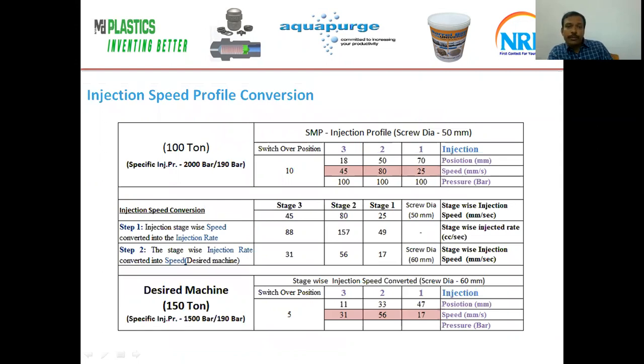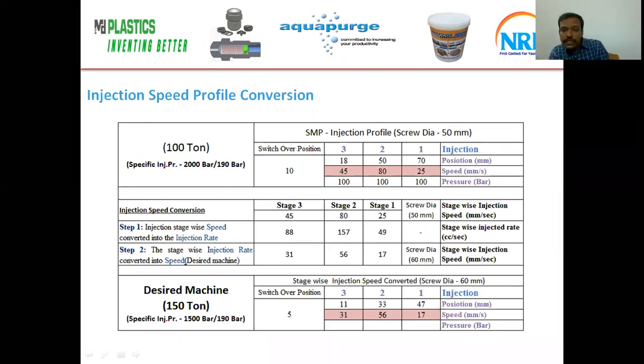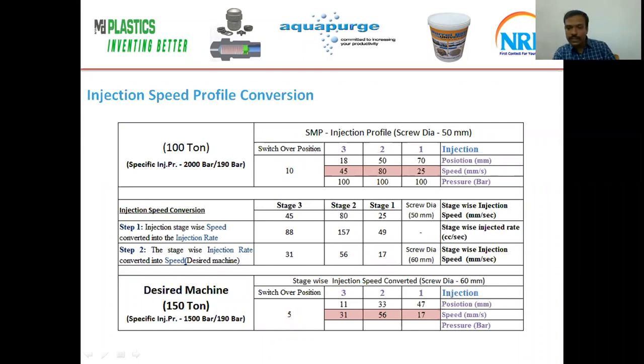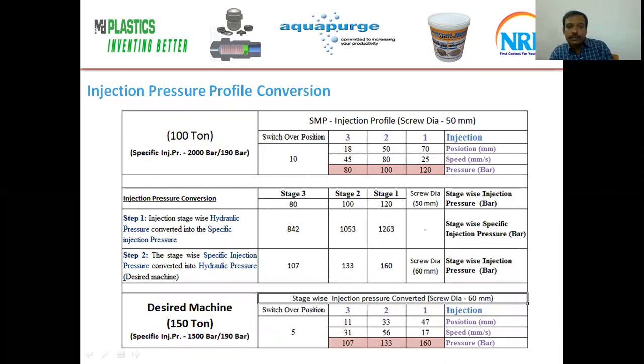Next, injection speed profile conversion. Now we know how to convert injection speed into injection rate, and we follow the same way here. The injection speed of the 100 ton machine is converted into injection rate: first stage 49 cc per second, second stage, for 80 mm per second speed, 157 cc per second, third stage 88 cc per second. Finally, the injection rate is converted into speed for the desired machine using the screw diameter. So the speeds obtained are 17 for the first stage, 56 for the second, and 31 mm per second for the third.